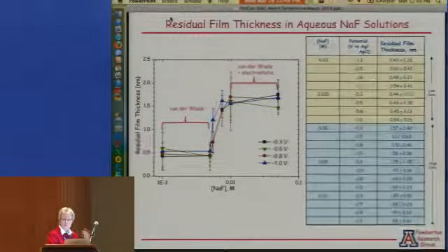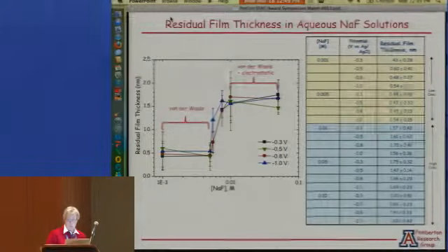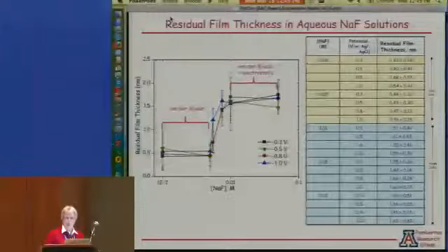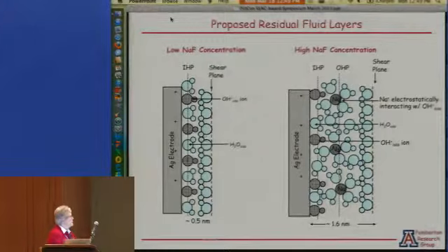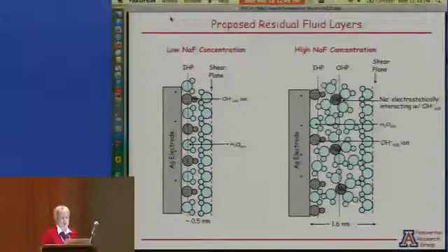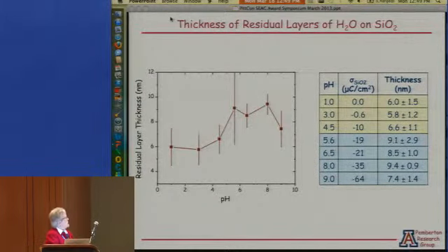There is some difference because there are structural forces we know that we're not accounting for, but all in all, when you use the theory of disjoining pressures to explain the forced dewetting process, as we're now calling it, you get a very satisfying result in contrast to the hydrodynamic. So at the end of the day, we can explain these thicknesses that we see in these two different concentration regimes, which is excellent.